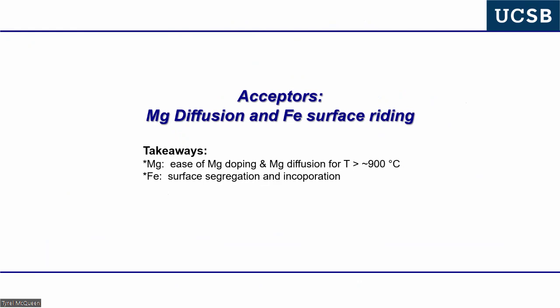Okay, so let me tell you a couple material science stories. Okay, and this is tied to material purity and doping. Okay, and so the donors we intentionally put into the material to make it conductive. Okay, we either put in a very high concentration to have contact layers that we spread current, and we put down ohmic contacts. We do very light doping because these are the layers where we have either a junction, a